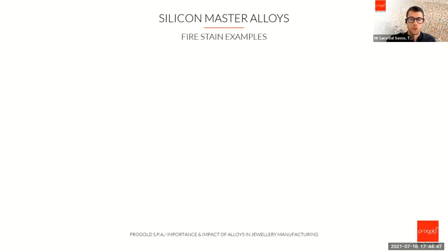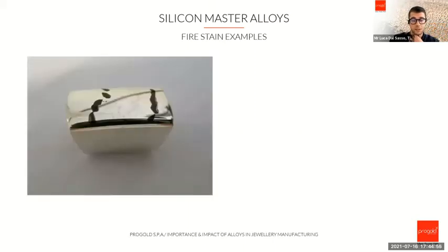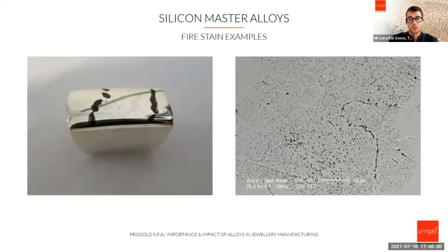Going on, we have another very known defect on jewelry, which is the fire stain, and which is very common because it's a built up or an accumulation of oxide in a large area of the piece. But the biggest problem about this defect is that it's very deep. So it's harder to remove. It's really hard to remove.